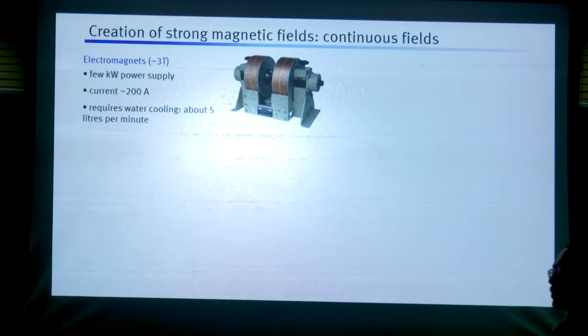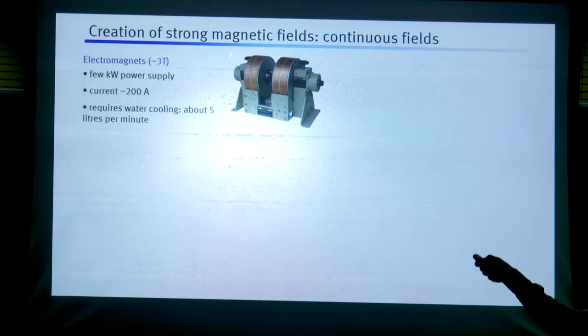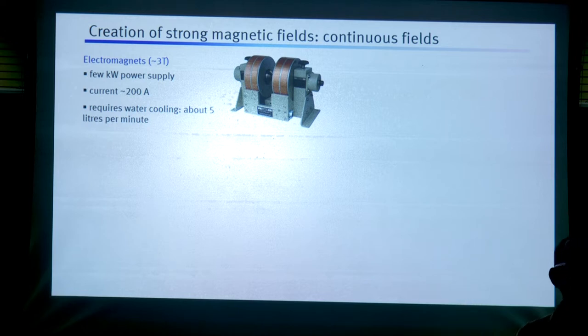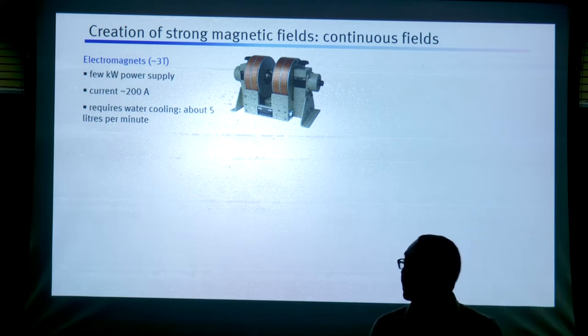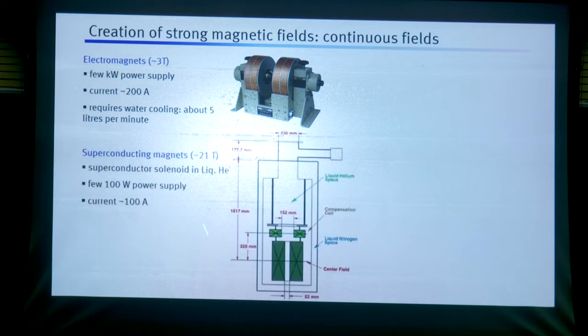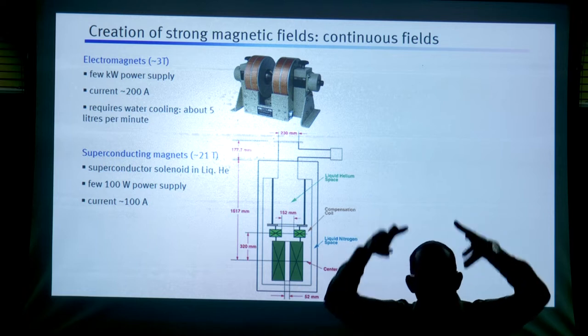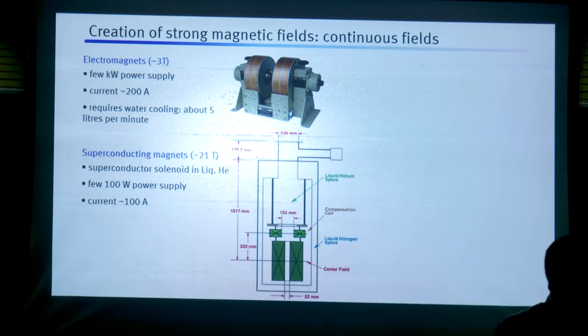Let's see how we create strong magnetic fields. Now, with such a magnet, which I showed you here, you can create up to like 3 Tesla. And you have to cool this magnet down. So you pass some 5 liters of water per minute, and you pass some 200 amperes of current. If you want to create larger fields, we use superconducting magnets, where there is a superconductor coil, and you immerse this in liquid helium. And this becomes a superconductor.